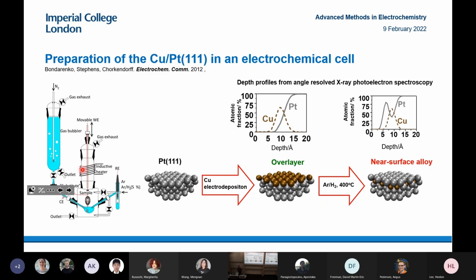And this has a similar effect to annealing the copper overlayer in ultra-high vacuum. Essentially what happens is that the copper goes into the second surface layer, and then you expose platinum at the surface. And we could tell this was actually the case from angle-resolved X-ray photoelectron spectroscopy. So you can see its depth profile.